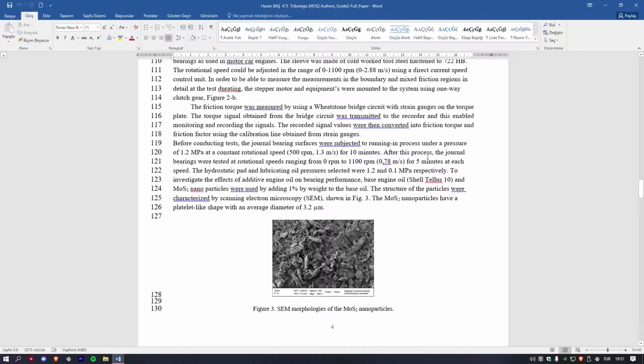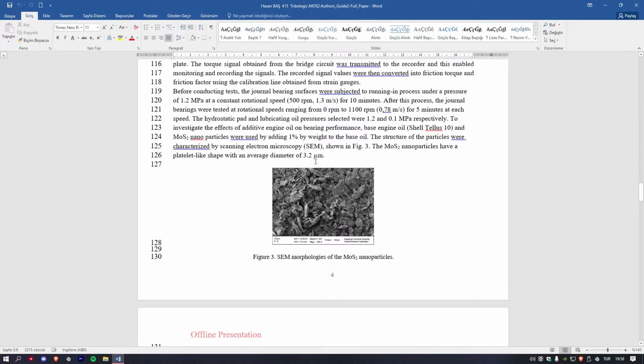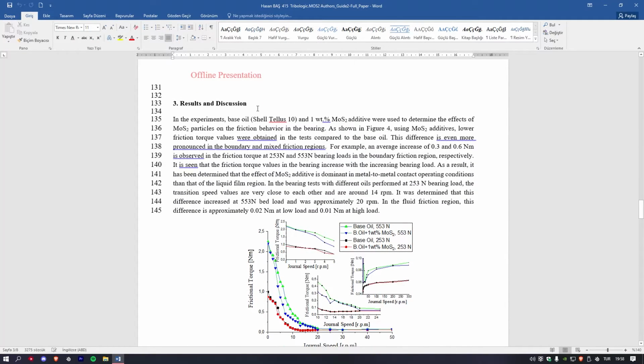After this process, the journal bearings were tested at rotational speeds ranging from 0 to 1100 RPM for 5 minutes at each speed. And then the structure of the particles was characterized by scanning electron microscopy, as shown in figure 3. The molybdenum disulfide nanoparticles have a platelet-like shape with an average diameter of 3.2 micrometer. Results and discussions.